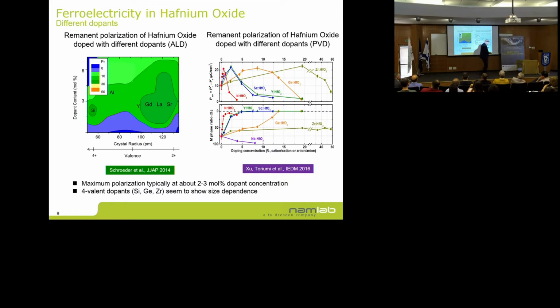So this work went on, and in the last couple of years, we looked at different dopants and different ways of stabilizing this effect. Actually, you can do it with lots of different dopants: aluminum, gadolinium, lanthanum, strontium. You can even do it with mixtures of zirconium and hafnium, which has become very popular because this is the easiest way to do it, with a very wide process window. From these data, this is data from ALD processes, this is data from PVD processes, the whole effect is very consistent. Even if not all the details are understood yet, we know today how to tailor the effect.